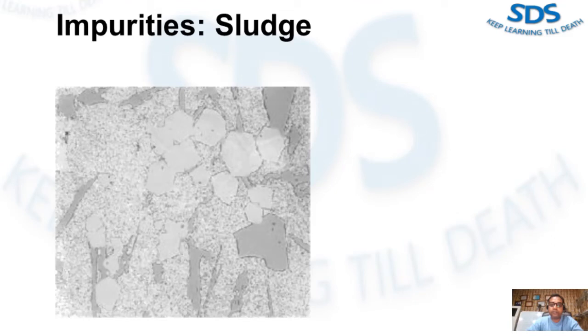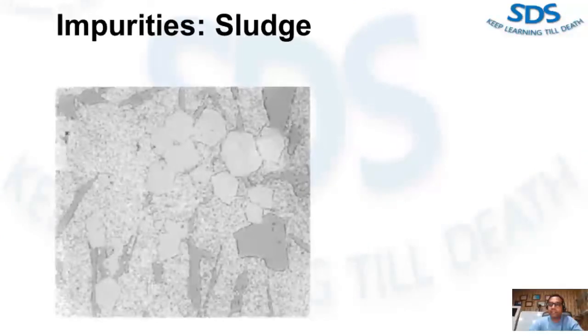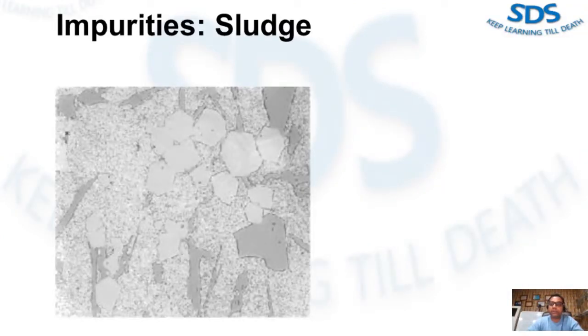How does sludge form in a melt? Iron is an unavoidable element present in die cast alloys. Iron has a positive effect in retarding die soldering, so a certain percentage of iron should be present to avoid soldering, usually 0.8 to 1.1 percent. Manganese has a favorable effect on the form of iron intermetallics and improved ductility. Chromium, though providing similar effects on structure and properties, can also be an unwanted impurity. In facilities where metal is constantly recycled, a gradual buildup of manganese and chromium content is inevitable, as neither element is refinable from the melt.